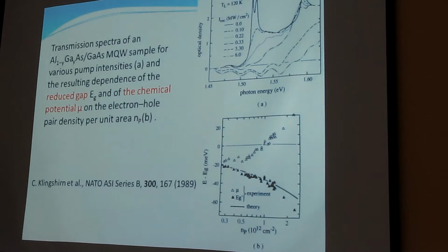Now, how do you measure the absorption spectra in this? There are two ways. Either you have to selectively remove the substrate by etching, or you measure photoluminescence excitation spectra and hope that it agrees with the absorption spectrum. Do you believe that it is? No, not always.